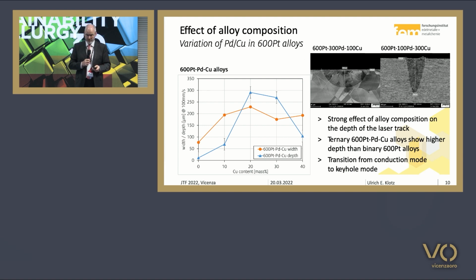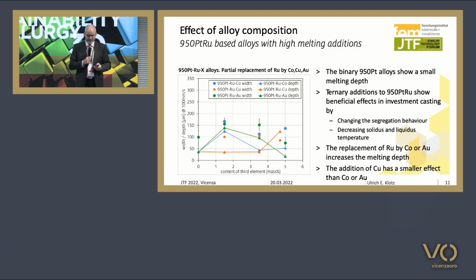Now here are some other examples. We used several ternary alloys based on 950 platinum ruthenium. In this first graph, I show some examples with high melting additions. We used copper, cobalt, and gold, replacing some of the ruthenium.